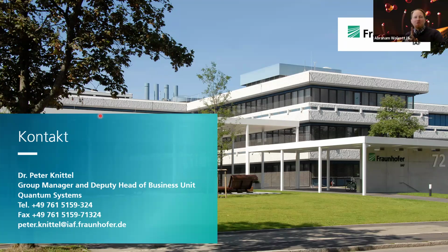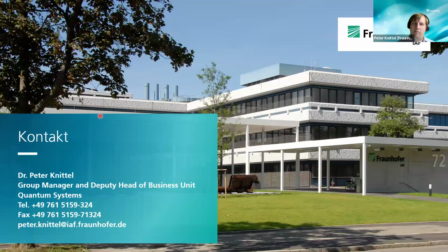Sorry, I don't want to monopolize your time, but you were talking about clustering. Have you witnessed a large amount of NV clustering or nitrogen clustering during your work? So what we see typically for low doped layers is that we get some kind of clustering of the NV centers to some extent, especially if you're having a step flow growth mode for 111, you actually see that the growth proceeds along steps. And at the edge of these steps, you typically see a higher amount of nitrogen being incorporated. So that's, or NV centers being incorporated.